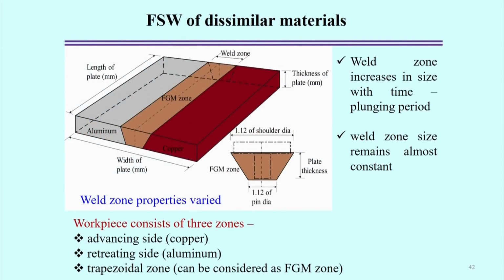So, apart from the different hybrid FSW technologies, now if we look specifically at friction stir welding of dissimilar materials, what typical properties do we observe in dissimilar welded materials? In this case, we consider an example of joining aluminum and copper. From the figure, the advancing side is copper and on the retreating side we generally put the aluminum, and there is a trapezoidal zone, which can be considered the zone corresponding to the functionally graded material, because at this point there is a mixing of aluminum and copper in between the two.